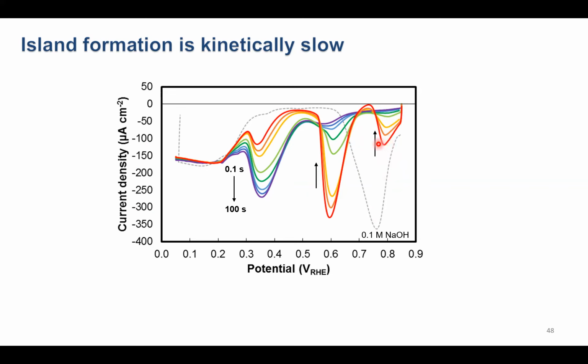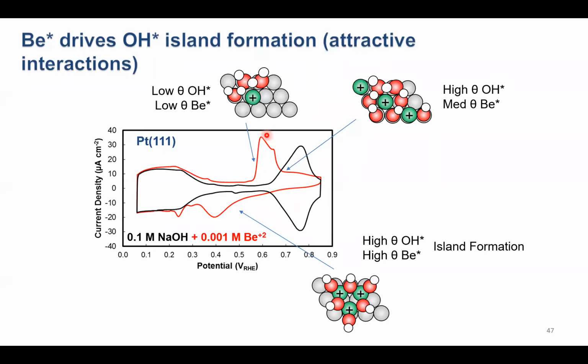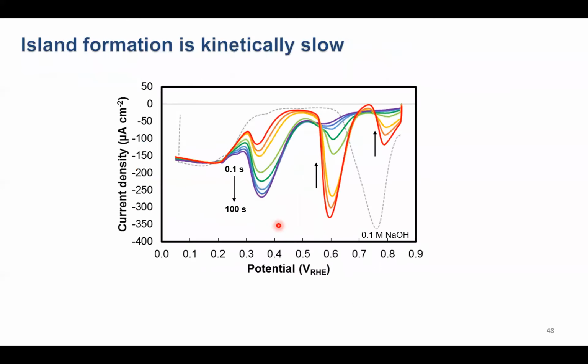Remember, we have only a trace concentration of beryllium in our electrolyte. The majority of our charge then appears in this second peak. I'm not showing it, but the potential of this peak lines up very nicely with the peak that we see in the forward-going scan. Meaning that if we scan very quickly, we don't have time to form these islands, and our peak is reversible, and we just have this slight promoting effect of a low coverage of beryllium on hydroxide adsorption.